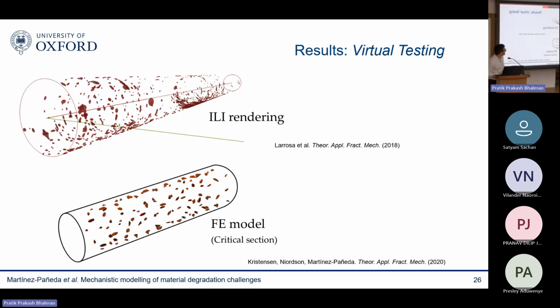For example, what you see here is a pipeline. It's a very long pipeline characterized by BP. All of those defects that you see there are pit corrosion defects. We can embed those defects very easily into our finite element model. We don't even need to create a funny mesh because you're solving for the phase field as a degree of freedom. So you can impose as an initial condition phase field equal to 1 where those defects lie, they have been properly characterized.